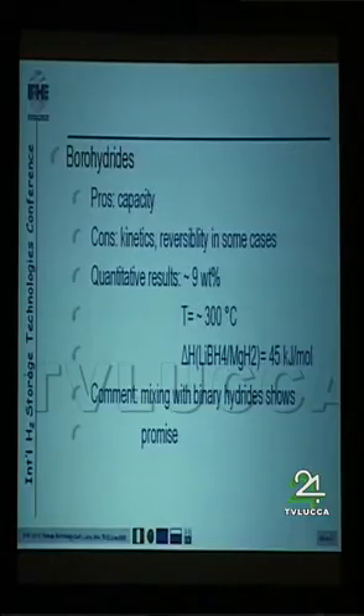Borohydrides. Pros are capacity; counters, kinetics, reversibility in some cases. Quantitative results good, about 9% in weight. Temperature rather high, 300 degrees centigrade. Enthalpies 45 kilojoule per mole. Mixing with binary hydride shows promise.